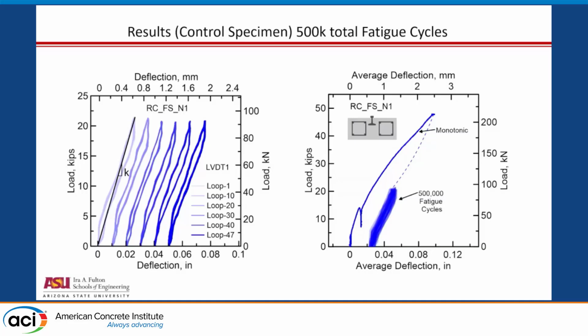And by checking the stiffness of the loading unloading at this stage versus this stage, we can actually see what is the total amount of degradation that has happened in terms of stiffness. So this figure shows, for example, the reinforced concrete section. And so we basically went up to about 500,000 cycles. And at that point, there was large enough deformation in the section that required us to pretty much stop the test and not go forward with the test anymore. In other words, the load was purely carried by the steel, and then the stiffness was basically suffering from that when you compare the 2 responses.